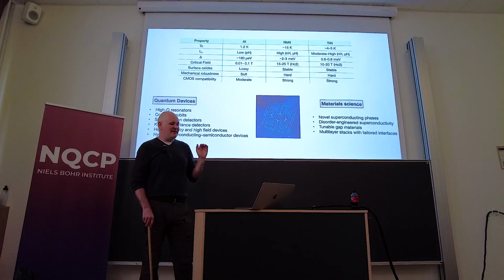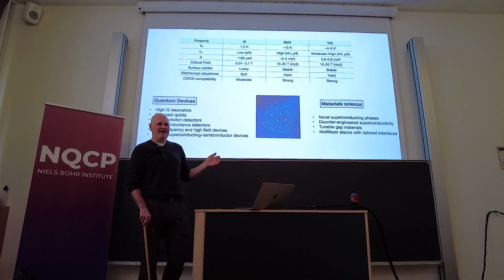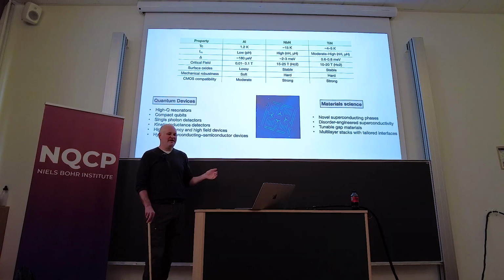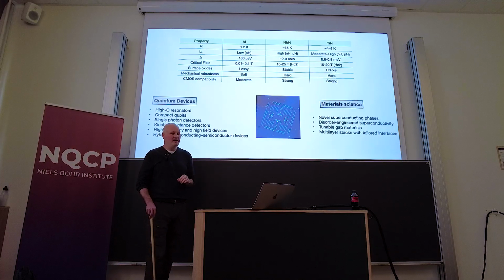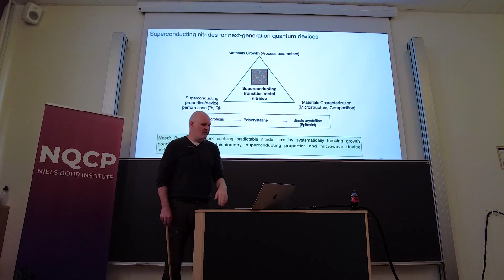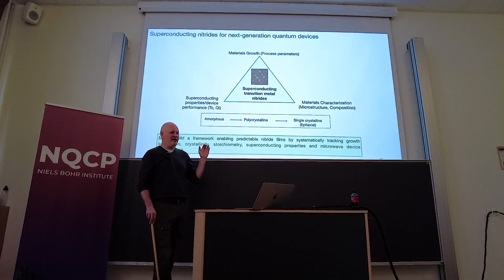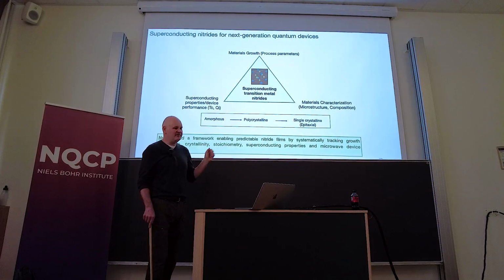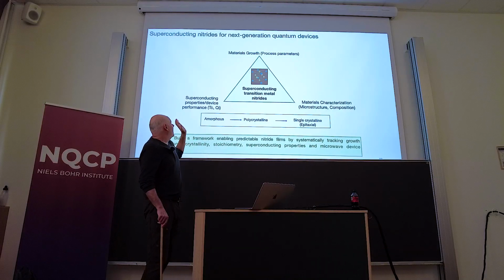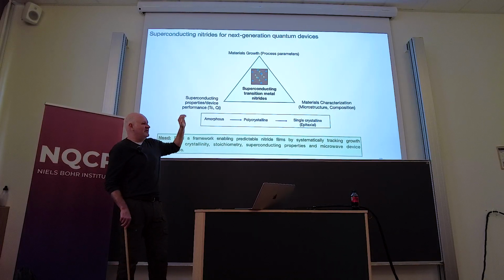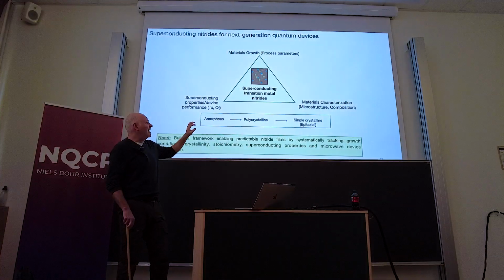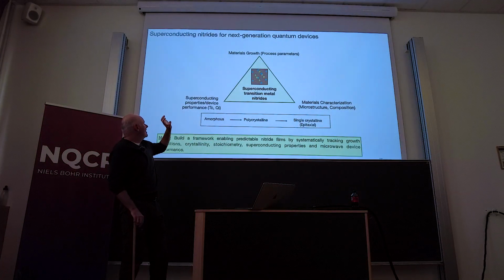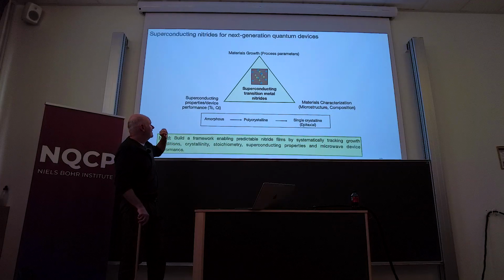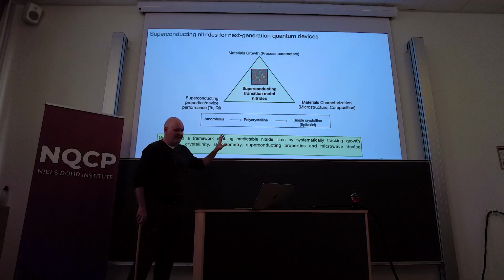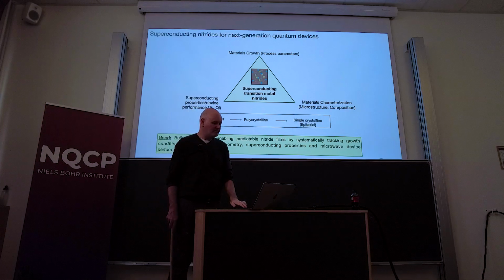But it's not something that you can transfer to a nitride easily. So the place we decided to start was actually on just looking at the nitrides themselves for things like the resonator circuitry. And so we went through quite a large process of exploring and developing these nitride materials. So doing materials growth. So this is all reactive sputtering, changing parameters, doing materials characterization, and then superconducting properties. Mostly this is TC, but you'll see we do some resonator measurements as well.